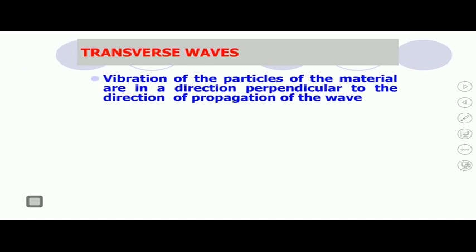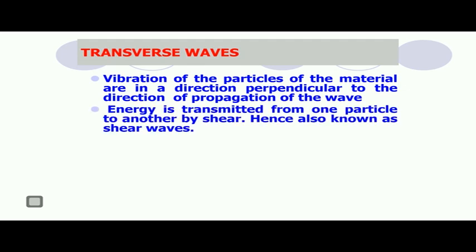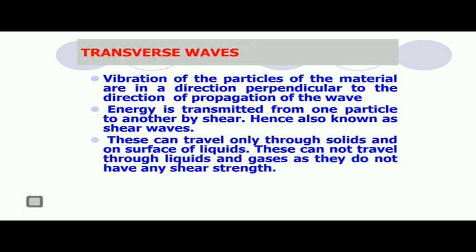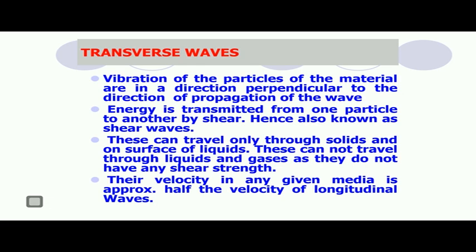Transverse waves are waves wherein the vibration of particles takes place in a direction perpendicular to the direction of propagation. The energy is transmitted from one particle to another by shear action, and hence these waves are also known as shear waves. These waves can travel only through solids and on the surface of liquid. They cannot travel through liquid and gases as these do not have shear strength. Their velocity in any given medium is approximately half the velocity of the longitudinal wave.